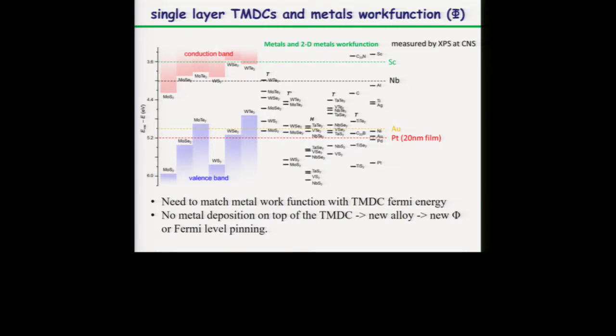But in reality, it's not as simple, because once you deposit the metal onto a single layer material, what you end up doing is breaking bonds, and at the end, the metal will have a different work function at the interface. So what we have done here at CNS is we have characterized metal films and found out where the work function is. Instead of depositing the metal on top of the TMDC, we do it the other way around. We deposit the metal first, and then we transfer the TMDC on top of the metal. In that case, we eliminate this problem of the metal destroying the 3-atom thick semiconductor. We have characterized that platinum is one of the largest work function metals, and the one that works well for tungsten diselenide, for example, and that's part of the data I will show today.